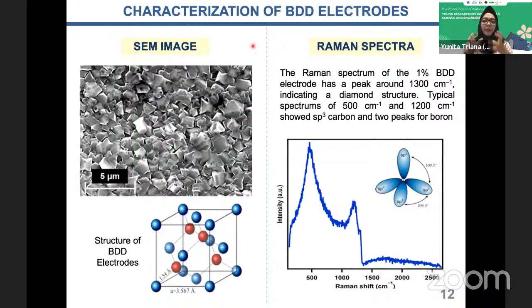After I made BDD, usually we see the appearance by SEM image. The purpose is that we would like to see the size. If we get a similar size, it is usually good, but not from SEM alone. We also take the Raman spectra. For example, 1300 is for the diamond structure. The diamond is already shaped in the structure, and the typical spectrum at 500 and 1200 shows sp3 carbon and 2 peaks of boron. So 500 here is the boron, and 1200 near here.